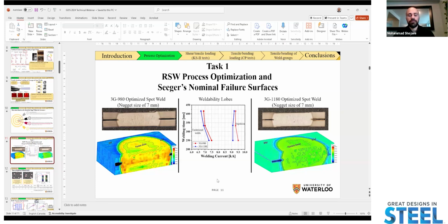We also have a paper that's directly analyzing these and addressing all the different phenomena that are happening in different regions. Especially, what was really interesting to us was the secondary hardening in the 980 and the softening in the 1180. And we've done extensive TEM analysis on that in our lab. And what we saw is that we have carbide particles that are forming that are responsible for the hardening that we're seeing in the subcritical HAZ region. Okay.